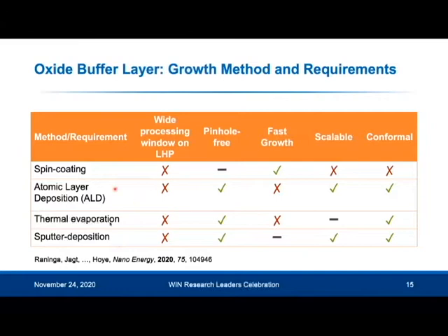Now, with these oxides, the role is not just to mechanically protect the perovskite device. The oxides also are electronically integrated with the device, and they have to transport the photo-generated carriers. So the electronic properties are also important. And for those of you who have worked with oxides, you would know that, as a rule of thumb, the higher in temperature you can process the oxides, the better the electronic properties. And that works if you're growing onto glass. If you're growing onto a perovskite solar cell, then you're much more limited in what temperatures you could use, because the perovskite is not thermally stable. And so far, the maximum temperature people have been able to use is 110 degrees Celsius, which at the same time significantly restricts what mobilities you can achieve with the oxide buffer layer. So that's the main problem.